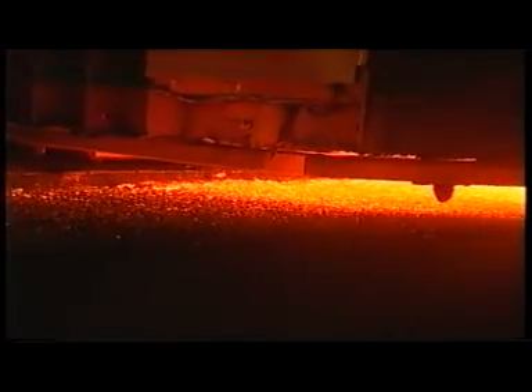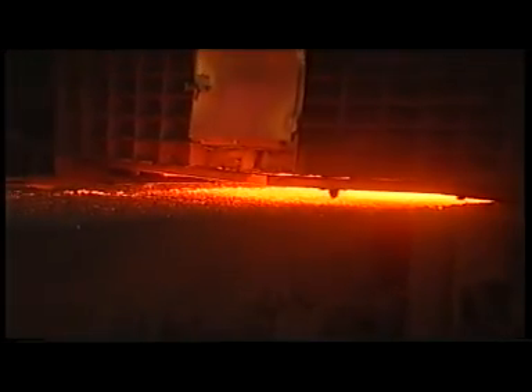There are 7 sintering machines in the Egyptian Iron and Steel Company works in Helwan. Their productive capacity reaches 3 million tons per year. By increasing the temperature of charge to 1250 degrees centigrade and by a horizontal movement, the sintering process proceeds on from up to down until it embodies the total thickness of the charge.